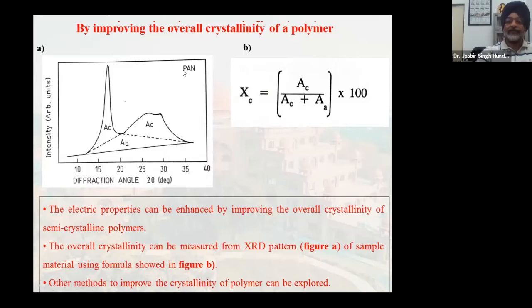This is in case of not SAN or ABS. It is in case of polyacrylonitrile. So we find that this is one very broad peak. Then there is another broad peak. That means you have crystallites of different sizes basically. So this AC represents the area under these peaks, and AA represents area under the amorphous region.